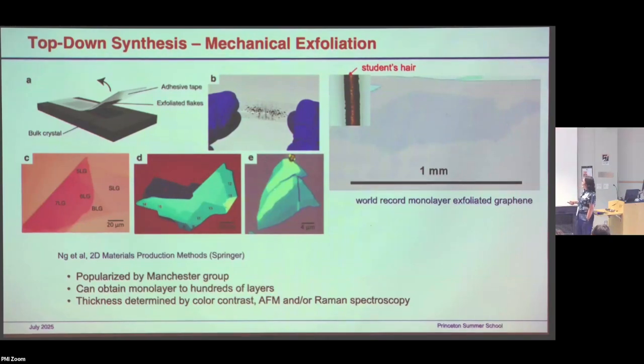Okay, another thing is that you can check the monolayer film by the color on the substrate. Especially for conductors, it's actually pretty obvious, well, obvious after you got trained. For semiconductors, it's more difficult. This is because of the interference between the light reflecting off your 2D material and the light that goes through the 2D material and reflects off the substrate.